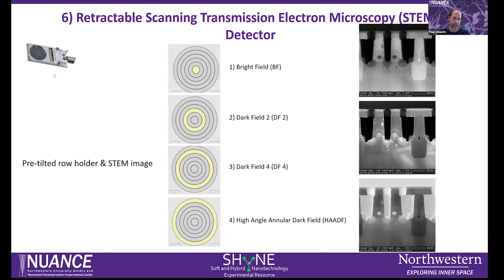This detector can, for example, be beneficial if you're creating a TEM lamella. Before you put it into TEM, albeit at lower accelerating voltage, you can get an impression of how the quality of your sample looks like in the FIB-SEM.